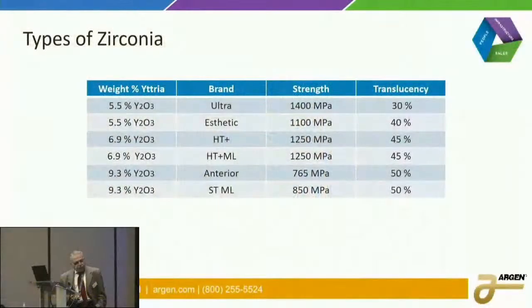The Anterior was introduced, and you can see here the translucency is very high, and this material is restricted to 3 units, no more than 3 units, because of this strength level here. This happens to be high for this particular material. Most companies sell this at like 650 or so, or even lower. But in our case, we got 765. And then when we made our multi-layer one, we were actually able to increase the strength a little more and keep the translucency. So what we're seeing here is a natural progression. I'll show you some other companies' materials as well, but it shows a natural progression. We show a strength increase and a translucency increase, which is what we're trying to accomplish.